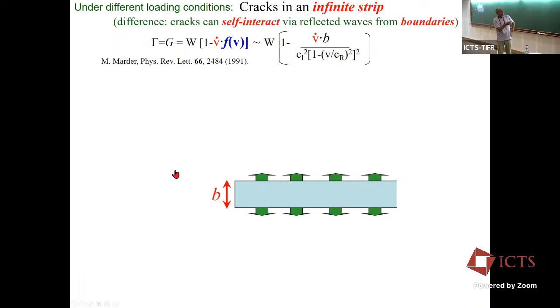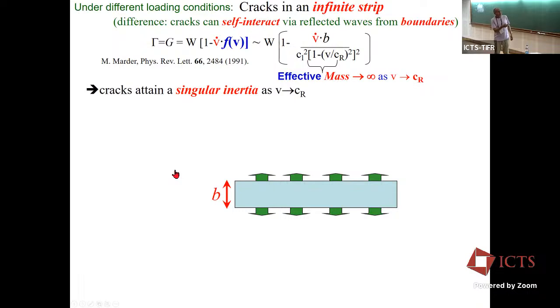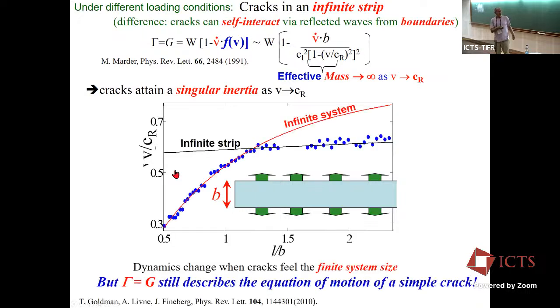So when you calculate this, and my friend Mike Marder did this, he derived this equation of motion in the early 90s, and everyone kind of ignored it because it didn't seem to agree with the classical equation of motion. One salient fact was that a crack is still limited by the Rayleigh wave speed, and the reason is that it develops an effective mass. This is a singular term that explodes when the velocity approaches the limiting wave speed. So the crack gets heavier and heavier. Actually, it gets inertia, but the inertia is what in this model limits the speed, and it actually seems to work.